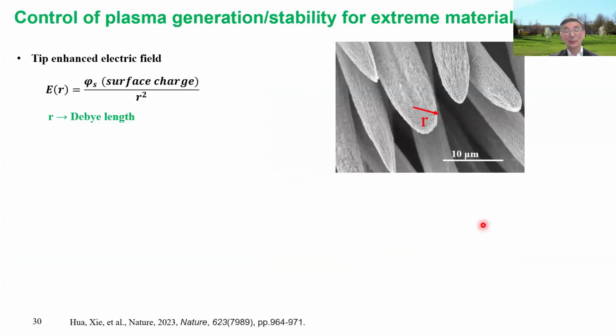And then I try to say how we can build a uniform plasma by understanding the combustion chemistry and plasma physics. In plasma, there is a length scale called the Debye length. At this length scale, any change of charge will be shielded, and equilibrium plasma only happens when the length scale is bigger than the Debye length. So what if we create an electrode with a lot of fibers, each fiber around a few microns, which is equivalent to the Debye length? Then you can generate a far non-equilibrium plasma near the surface, and you can control plasma non-uniformity.